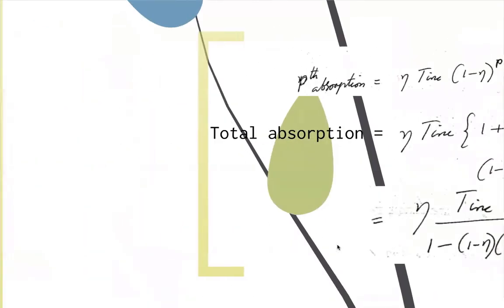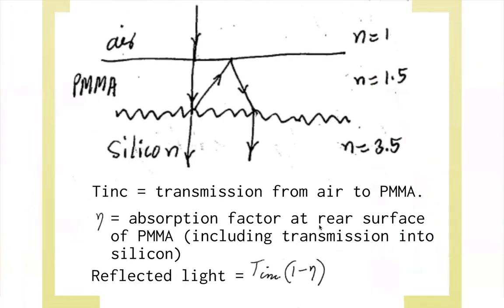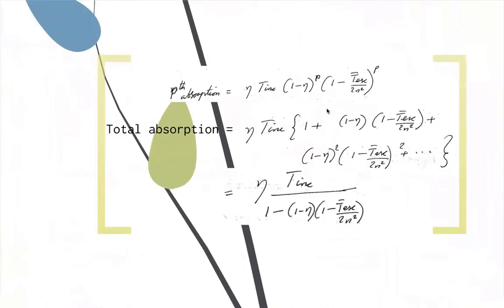So let's make sure we understand what we are just talking about, right? If we put a PMMA coating on top of textured silicon, we can get 92.3% of the light to go into the silicon. Now recall, if we don't do anything, in other words, if we compare this to just bare silicon, we know that about 70% of the light will be absorbed, right? That's this number here.